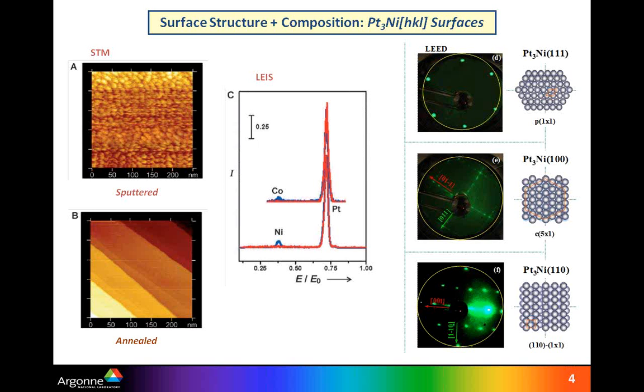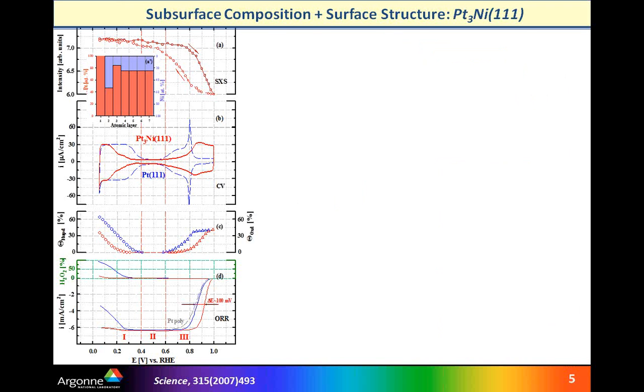On the left-hand side are our new results. These are STM results, which show that in addition to the UHV LEED investigation, we can now also see the surfaces, especially in an electrochemical environment. Before these STM images, we were focusing a lot on X-ray diffraction and scattering, and this slide is just showing some results, a combination of X-ray scattering and electrochemistry.